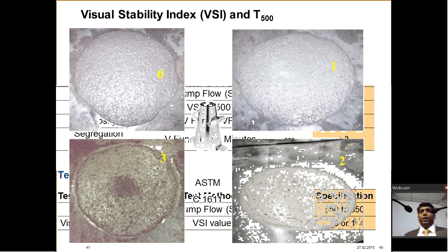If the concrete is segregating, you will find a small heap of aggregates in the center and a lot of bleeding on the sides. This concrete is not allowed, reject. The other type could be highly soupy concrete. You have a slurry, the aggregates are uniformly spread, which is okay, but you can see slurry leaking out more than 10 mm beyond the periphery of the concrete. So this is also not acceptable, reject.